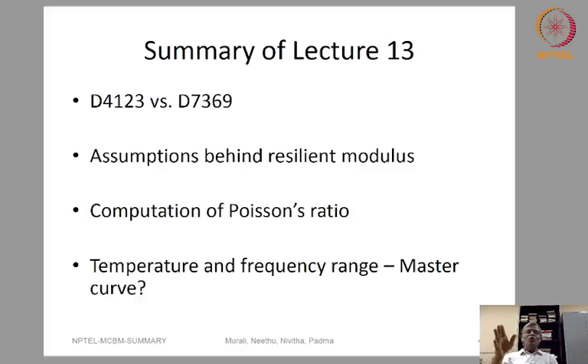What do I mean by yes? If you understand how this test method is conducted, the assumptions behind the theory, and if the material that you are planning to use is more or less following these assumptions, you can do it. But when I say no, what it means is the standards, the procedure that is prescribed here, is more tuned towards bituminous mixtures. Is it for cold mixtures? If you are doing research and development, yes, you can do whatever you want. But if you are a practicing engineer and you want to really find out whether one can use it for cold mix, I will advise caution here, because the cold mix can also behave like a granular material. So this particular test method may not necessarily be suitable to you.